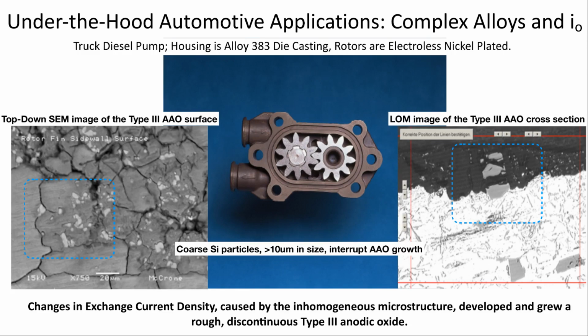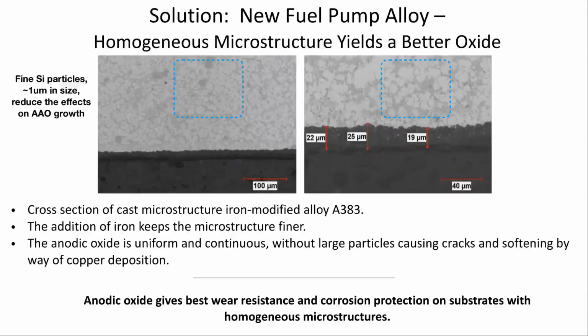And remember what I told you: equilibrium processes will become something to worry about when we exceed the polarization wave. Well, copper that had gone into the electrolyte redeposited on top of the surface of the oxide in areas where resistance was highest. The image on the right is a metallographic cross-section of this material, where you see quite well the size, shape, and distribution of large primary silicon particles, as well as silicon needles and other large particles.